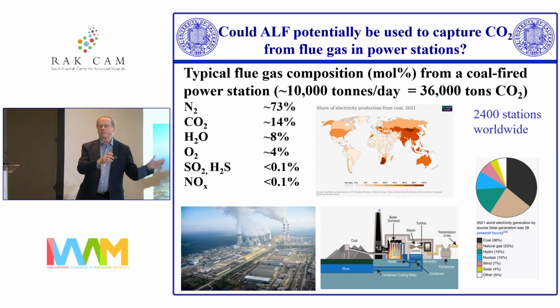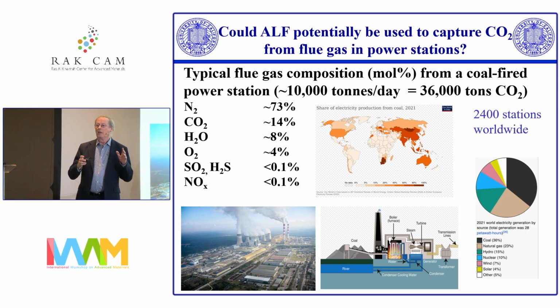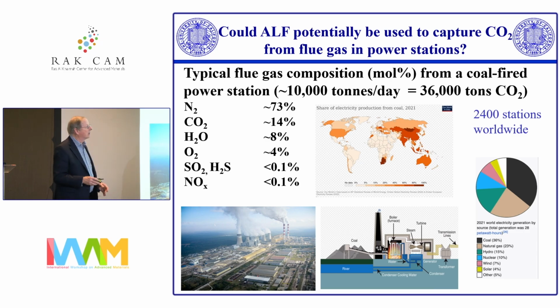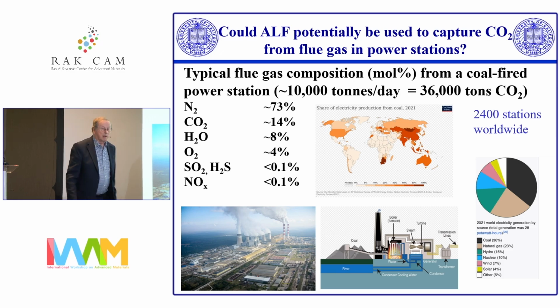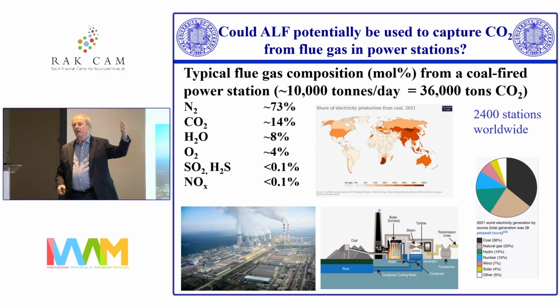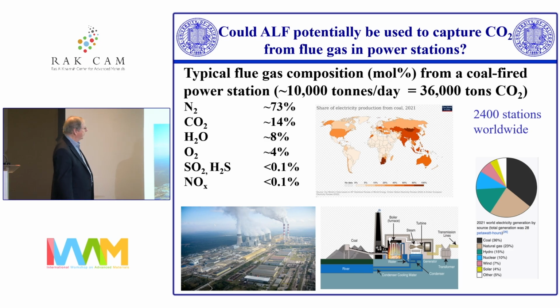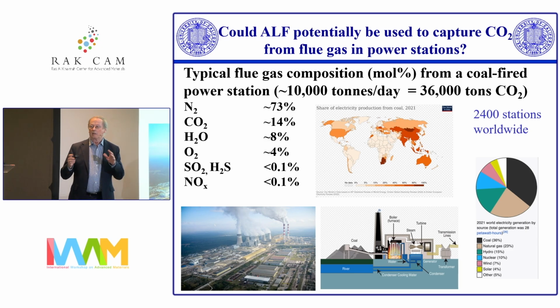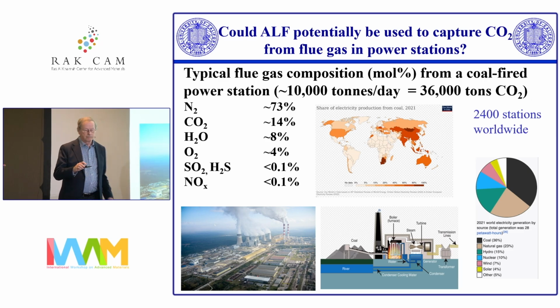And that's one of the reasons that I like ALF, because if you're going to address a problem like the CO2 problem, then you have to be scalable and simple. Otherwise, the quantities of material that you need are out of sight. But the challenge here is that the flue gases contain a certain amount of water, or steam, of course, since it's in the vapor phase. And most MOF-type materials are unstable in steam above room temperature.